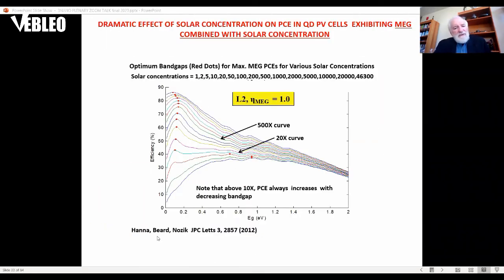Now, an important effect, which is very surprising in how dramatic it is, is that if you combine solar concentration with multiple exciton generation and then apply the theoretical Shockley-Queisser analysis, you can get the same plot as Shockley-Queisser, which is shown down here with an intensity of 1. Each curve has a higher intensity from 1 sun to the maximum concentration you can develop, which is 46,300 suns. That would be if you had the solar cell on the surface of the sun, or in the interior, which you can't, but theoretically you just see how high it can go. But for achievable concentrations, which could be as high as 1,000, there are collectors for concentrating sunlight, either in PV applications or in thermal applications, to get concentrations of 1,000.